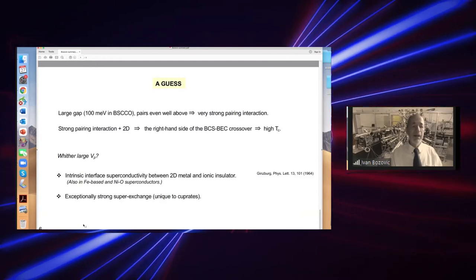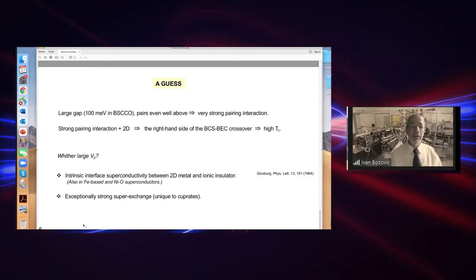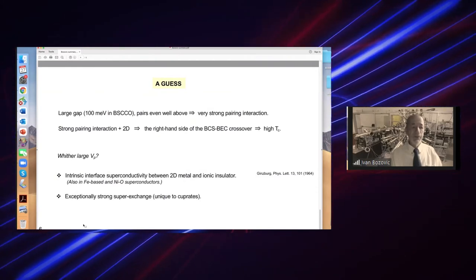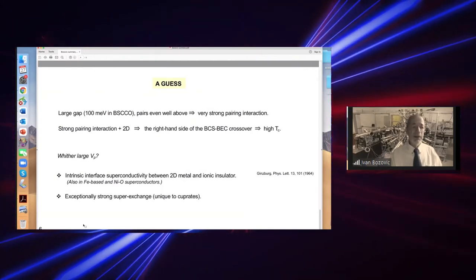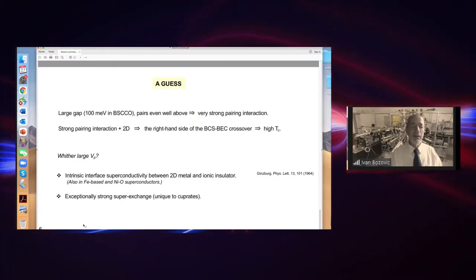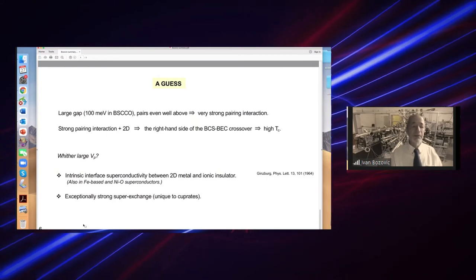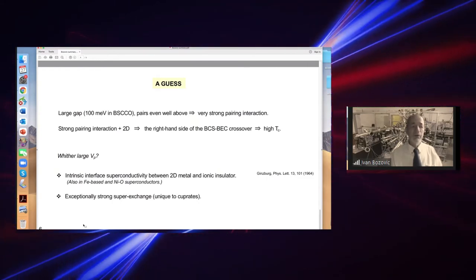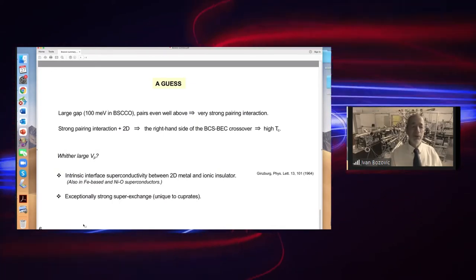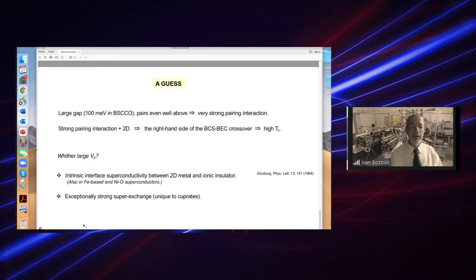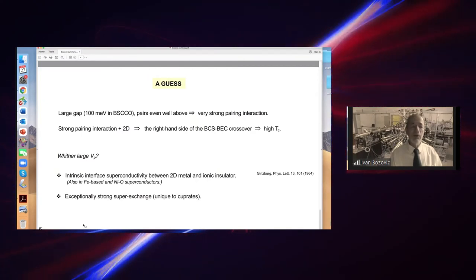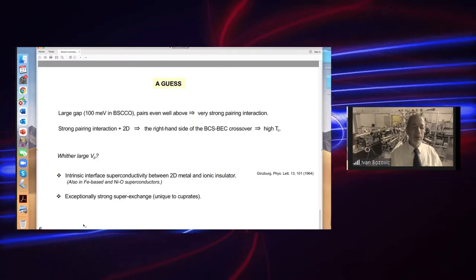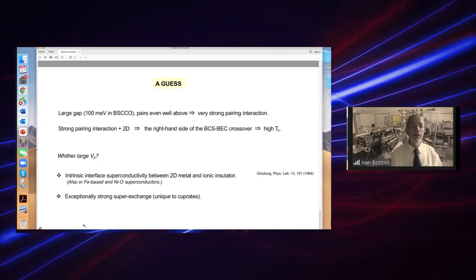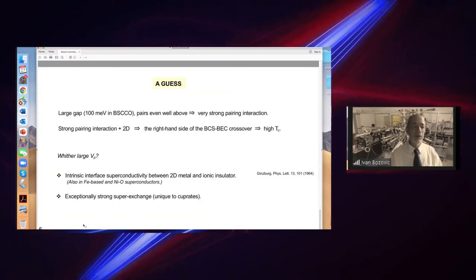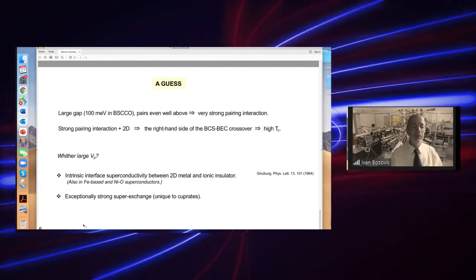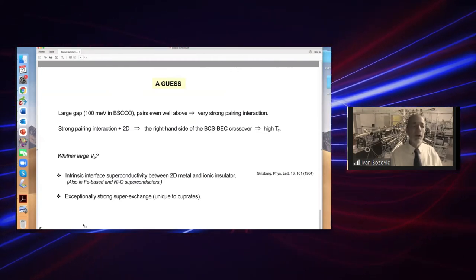So what can we say about our main question, which is why is Tc in cuprates so high? The answer is for two reasons. First, the pairing interaction is very strong. This is indeed directly seen in tunneling and shot noise spectra. And second, cuprates are quasi-two-dimensional. Both these facts favor BEC over BCS in the BCS-BEC crossover diagram. It seems, therefore, almost inevitable that we are on the right-hand side of the BCS-BEC crossover. And if that's the case, that would indeed explain why the Tc is so high.